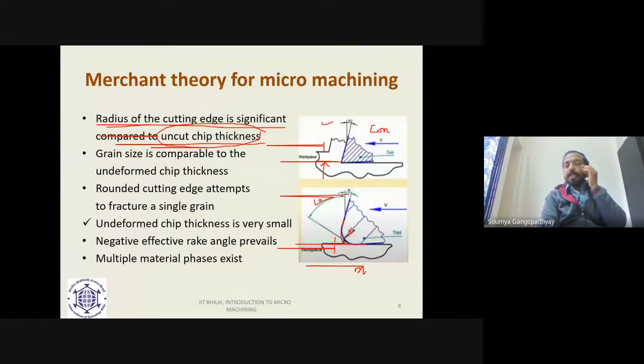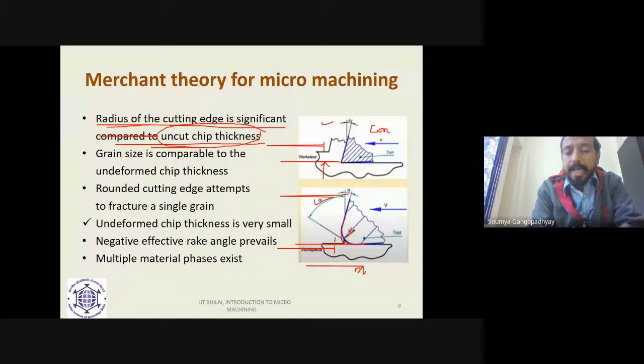Okay, so that means the edge radius and the uncut chip thickness are of similar order of magnitude, and therefore the effect of the radius of the tool gets amplified in the micro cutting domain. But then what happens in macro machining? In macro machining, it has the edge radius, and the edge radius typically ranges from 10 to 50 micron. 10 micron to 50 micron radius of the cutting edge.